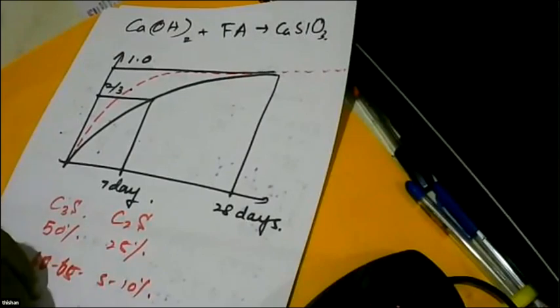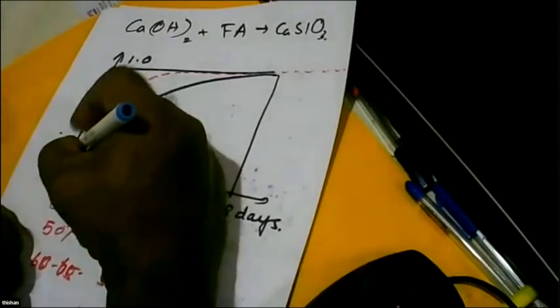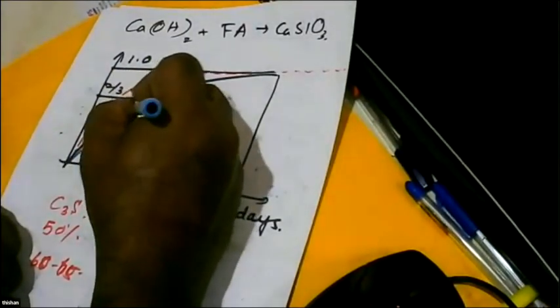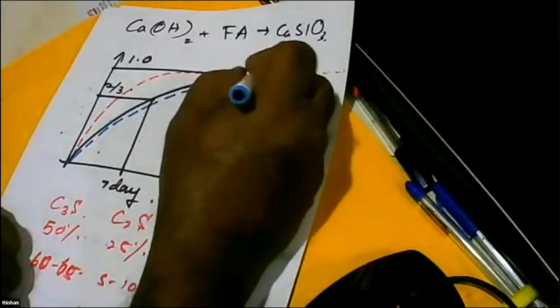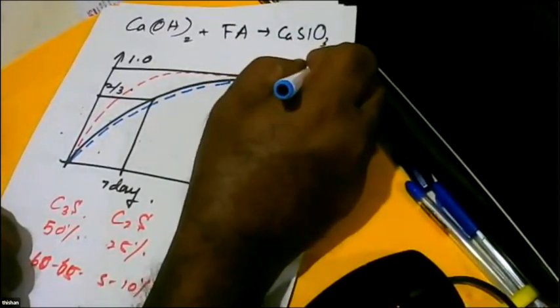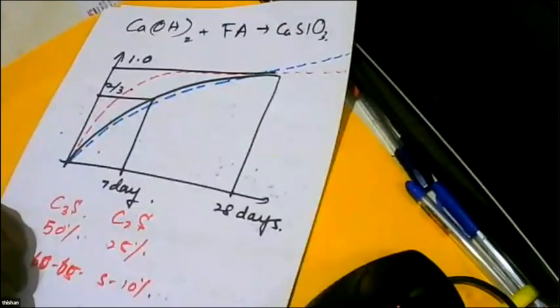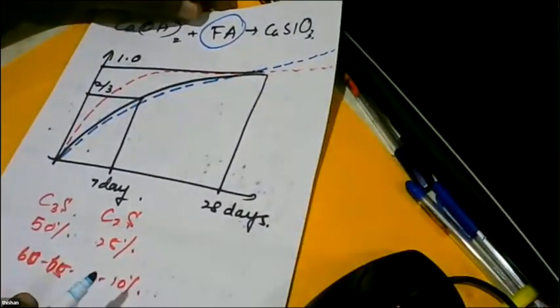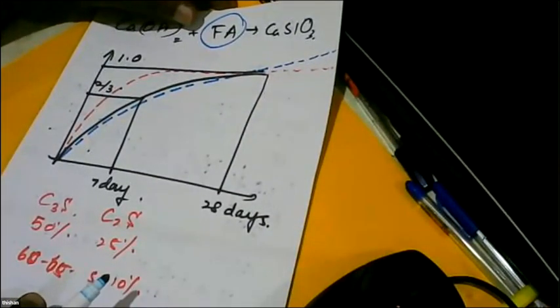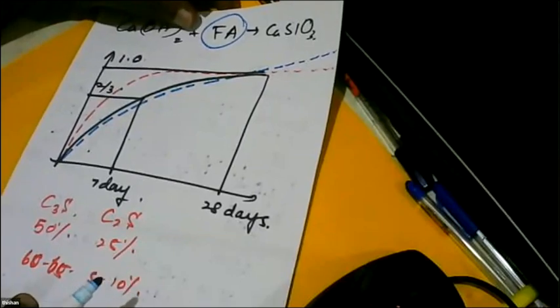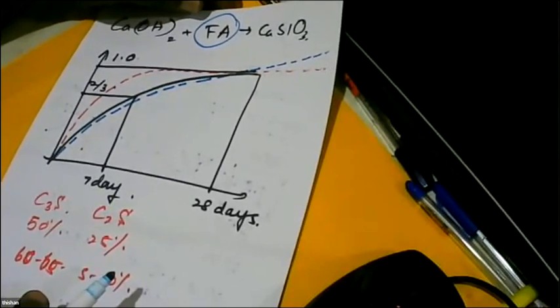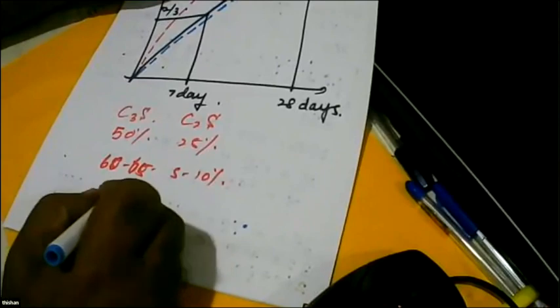But the moment you add fly ash, what happens? When you add fly ash, because we have less cement now, it will go more in a curve like this. But the advantage here is it will continue to gain strength. It will continue to gain strength because this reaction is going to happen beyond 28 days. So what is better? Using fly ash or without using fly ash? Using fly ash is good, and the percentage can be 10% to 25%.